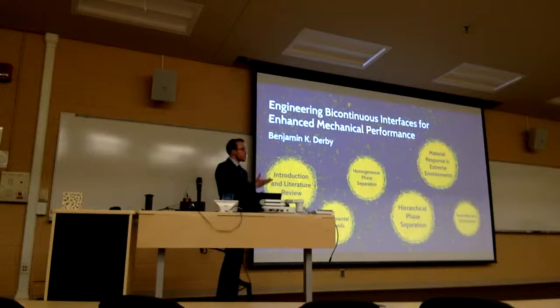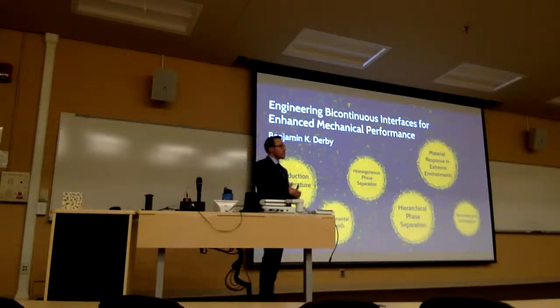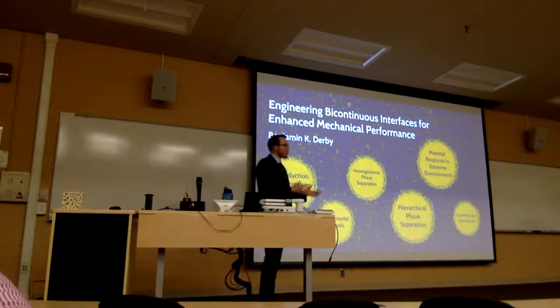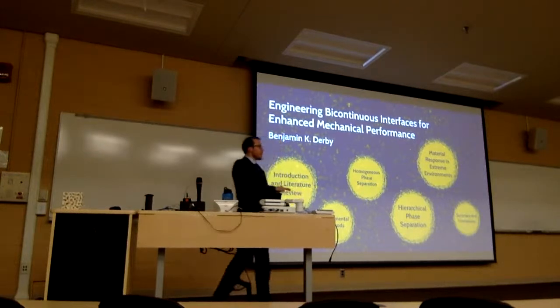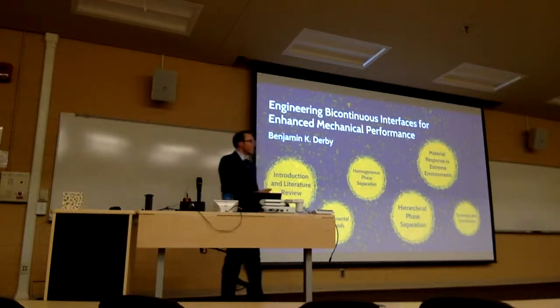Possibly what we could do, and we've played with this idea, is to deposit, say, an amorphous film of these two constituents, and heat it up during TEM imaging. We can actually have a heat holder inside the TEM where we can apply those thin films and possibly see the progression of phase separation. But during deposition, I don't know of any technique that we can use to do that. But that would be cool.